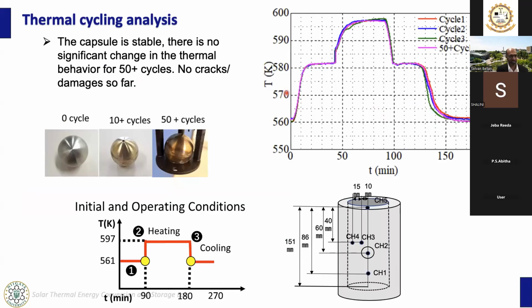The initial and operating conditions of the cycling tests you can see in this graph. As you can see, when the temperature increases and reaches the melting temperature, it is almost constant. As soon as the PCM material melted, the temperature profile increases suddenly. After this point, the discharging experiment was conducted. When it reaches the melting temperature range, it is almost flat, and as soon as the material is solidified, the temperature response is very quick.